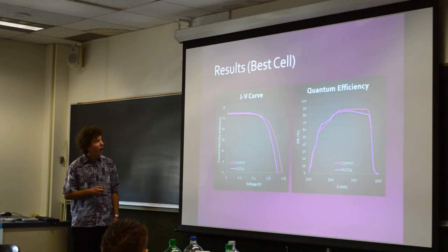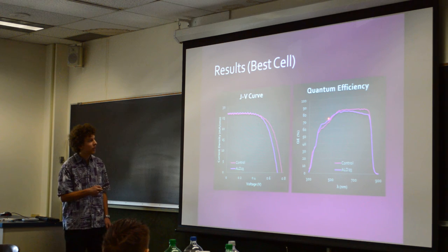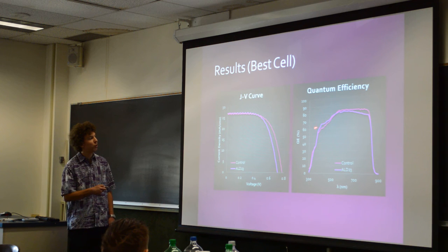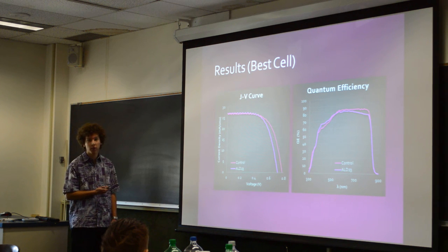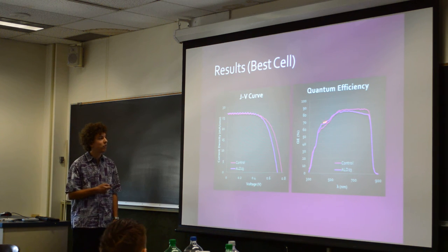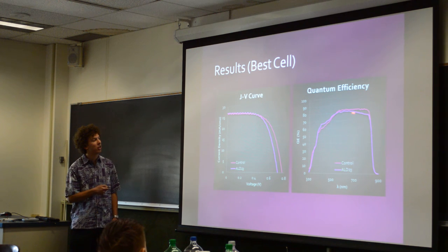And then you look at our quantum efficiency, and we actually have a slightly higher one on the blue side, which is surprising because we have the same CdS thickness, supposedly. And then you have a little decrease here in the longer wavelengths. So we need to fix that in the future.